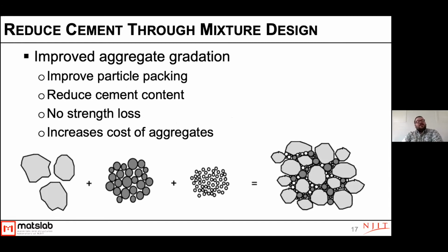Another thing we can do is reduce our cement through mixture design. So a typical mixture will have 500 or 600 pounds of cement per cubic yard. But we can actually reduce that by ensuring that our aggregates are well chosen for their size to make sure that we have less space in between them. So we actually need less cement, and we don't see any strength loss in this. Right now, this is difficult because it increases the cost of the aggregates because it requires our aggregate producers to make a different material. But again, as with all of these products, as it becomes requested more, those costs will go down.